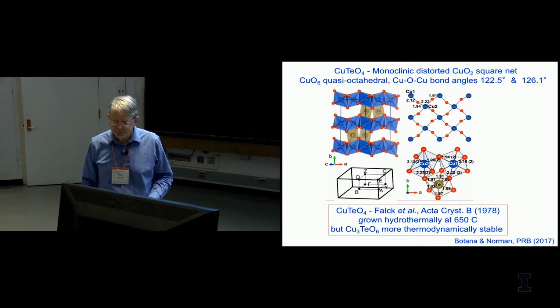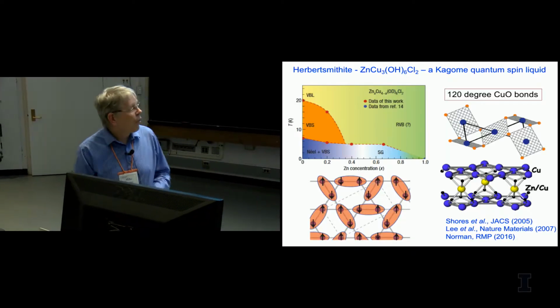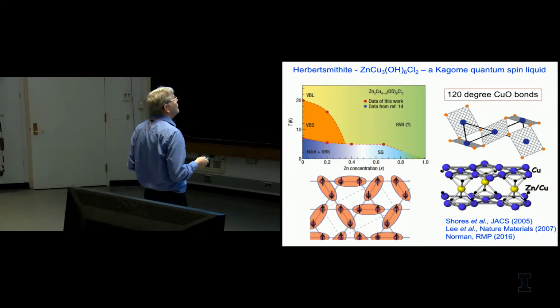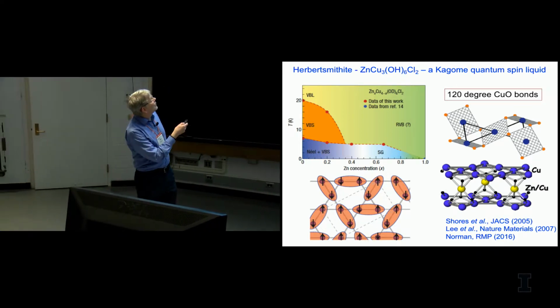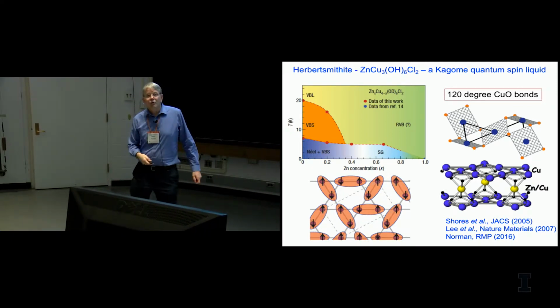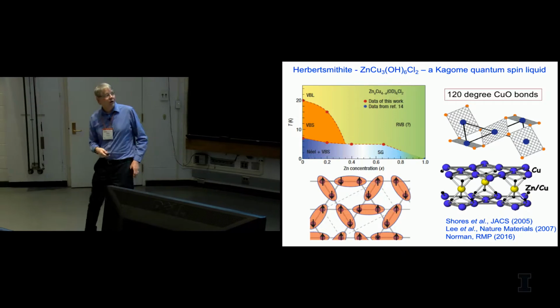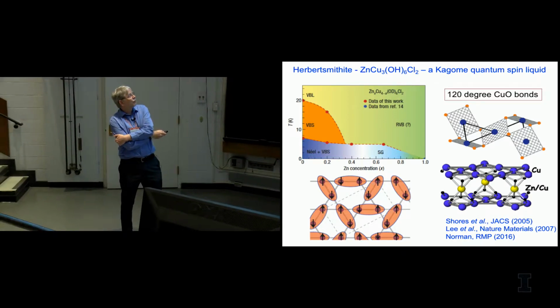So growing this material and then doping it by replacing tellurium by antimony could tell you a lot about what's going on. Of course, a real quantum spin liquid was discovered about 10 years ago by Dan Nocera's group. This is the so-called Herbertsmithite, which was a pretty rock that I showed on the cover of my first transparency. And this material actually has no long-range order, and the coppers sit on a Kagome lattice, which is a frustrated lattice, 120 degree bond angles. And again, people were thinking, wow, if we could dope this, do we get some sort of superconducting phase?